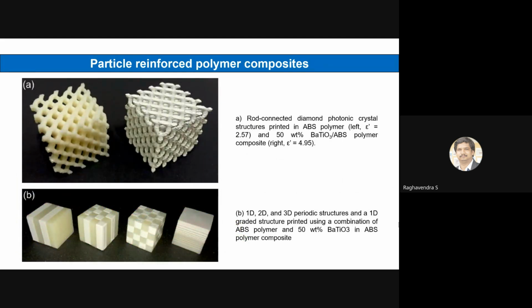This is one more example, where barium titanate is infused with ABS polymer, and you can see how much change there is in the relative permittivity, that is epsilon prime. With the normal structure it was 2.57, and by adding 50% barium titanate it has gone to 4.95. That is almost double. And if you further explore the study, if this percentage is increased to 70%, then the property enhancement is almost 240%. So whatever we are telling, the property enhancement is very significant. That is why this area is so promising. And in example B, you can see they have generated different structures like 1D, 2D, 3D periodic structures using the same composition.